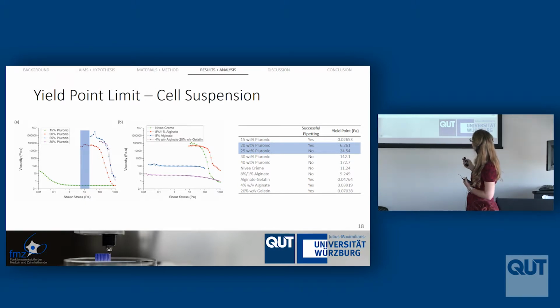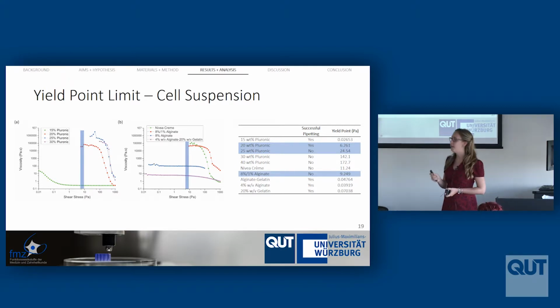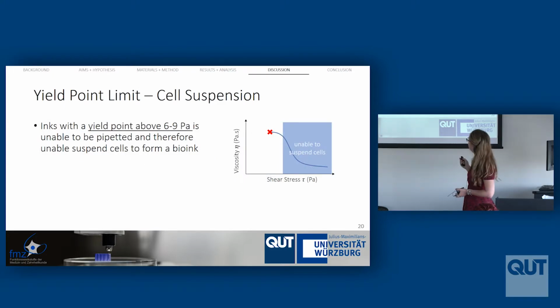And so we had 2 different formulations. One could be pipetted or suspend the cells, and one couldn't. So our limit has to be somewhere between 6 and 24 pascals. But then we can further define this because our alginate couldn't be pipetted, so it couldn't suspend the cells, but it had the limit of 9. So this tells us that inks that have this yield point, this particular point here, that's above about a 6 to 9 pascal limit, is unable to be pipetted and therefore unable to suspend cells.